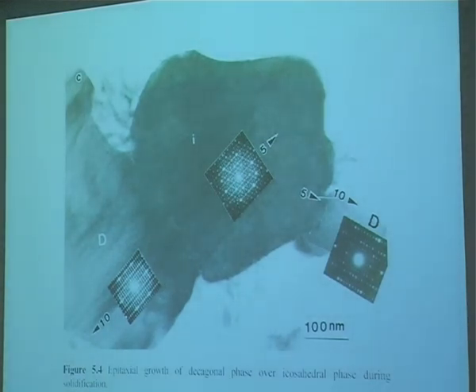This is not from our work, but it was inspired by the work that we have done. In the electron microscopy work that we did, we found an icosahedral quasicrystal and decagonal quasicrystal coexisting with an orientation relationship between the two. This is from Hiraga's work. The 5-fold axis is parallel to the 10-fold axis. It's very important that the quasicrystals are so closely related. Again, the whole question of an interface between a quasicrystal of a different type, a 2-dimensional quasicrystal and 3-dimensional quasicrystal, was explored in that, but not emphasized.